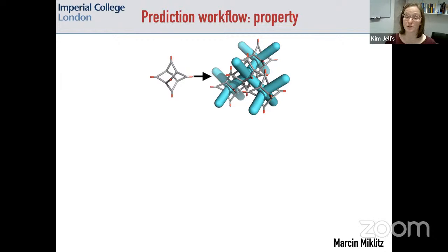Because if you had a guest diffusing through that diamondoid pore network, then the key potential rate limiting steps are diffusing in and out of the window, and then also diffusing around the corner of the center of the cage. Much like getting a sofa around a circular set of stairs or something, you've got to do that awkward turn. But you could predict how sorbates were going to behave within any hypothetical system by doing a lot of analysis at the molecular level.